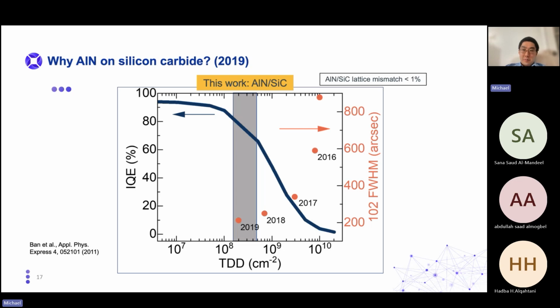And once the silicon carbide is removed, you can roughen the backside surface of the aluminum nitride to allow the emitted light to escape from the device, light extraction, relatively easily compared to even aluminum nitride and sapphire material. So light extraction is the main barrier to high efficiency UVLEDs today, because of total internal reflection in the interface between aluminum nitride and sapphire, or aluminum nitride and silicon if you manage to grow it on silicon. But basically, total internal reflection is what occurs at those interfaces, and unless you find a way to remove the substrate, it is very difficult to extract all the emitted light, and a lot of light ends up getting absorbed in the device.